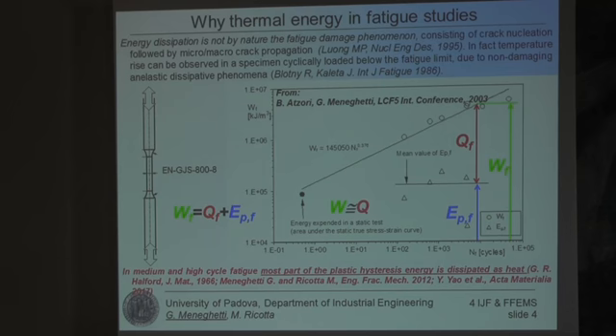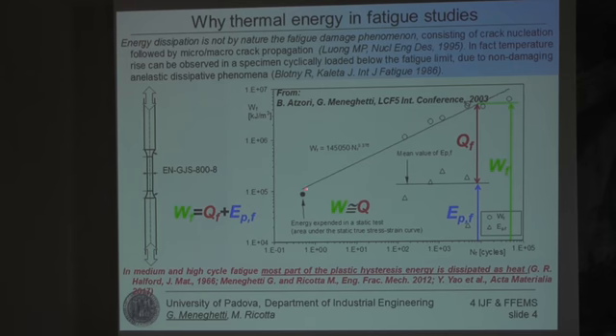Now, I want to show you these results that we presented in the low cycle fatigue conference in 2003. We measured the three forms of energy involved in fatigue by testing specimens made of an austempered ductile iron. So we started with a static test, and this is the energy expended to break the material in a static test. It is nothing but the area under the static stress-strain curve. And then we performed the fatigue tests in the low cycle fatigue, and we measured the total mechanical energy expended up to fracture. And you see here such an energy plotted versus the total number of cycles to failure.